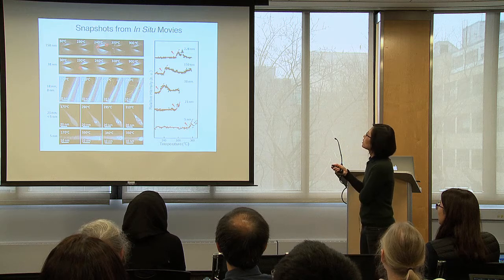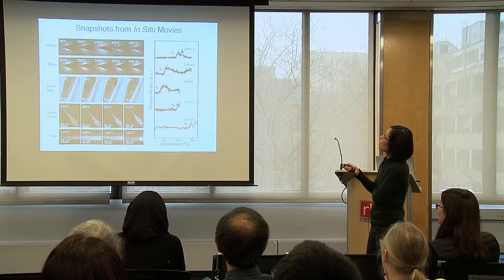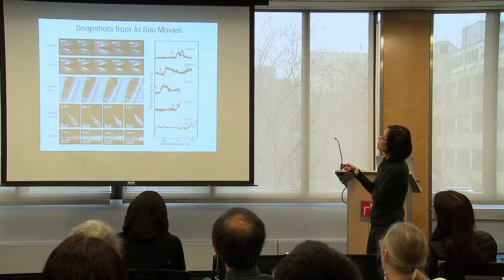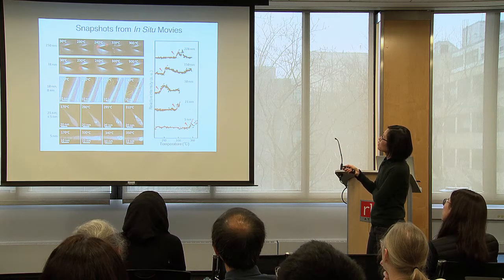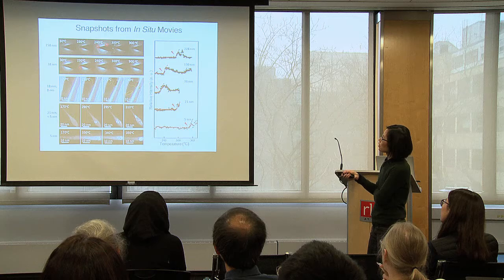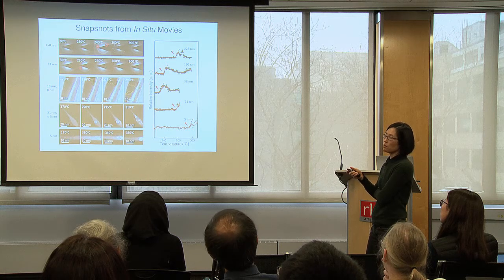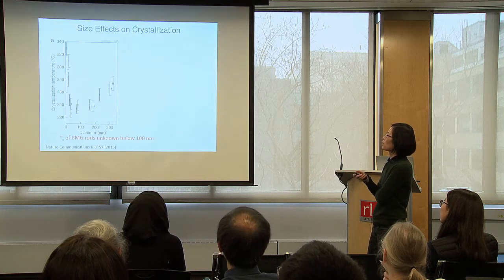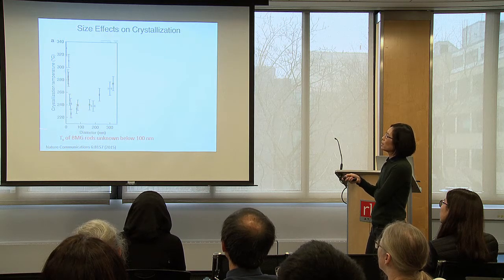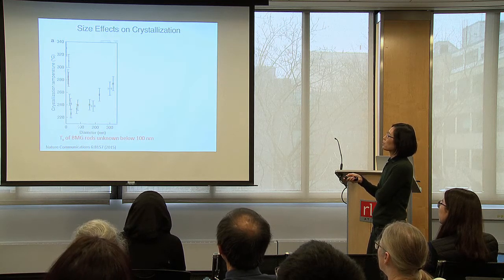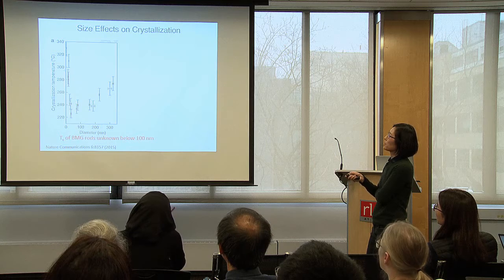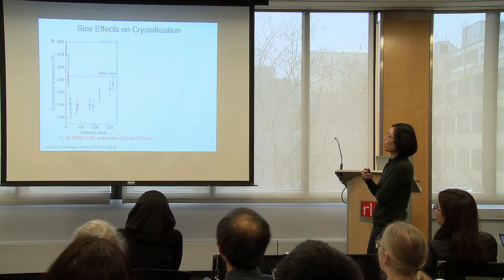So you see that as we initially decrease the diameter of the rod, the onset of crystallization decreases as well, but then it takes an upturn. So it has this non-monotonic behavior. Here's a summary as a function of the diameter of the nanorod, crystallization temperature. Here's the bulk value.